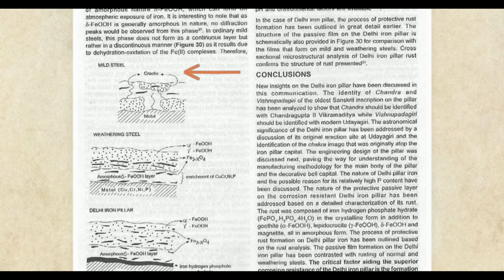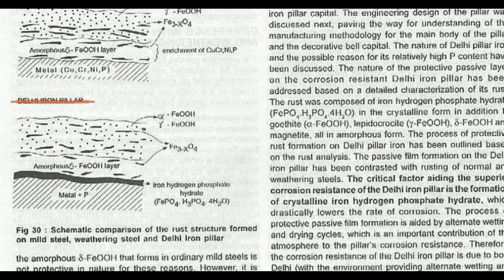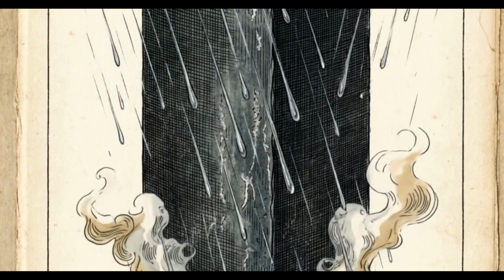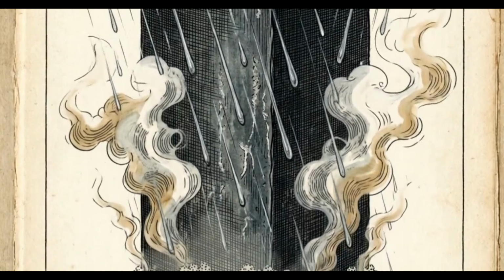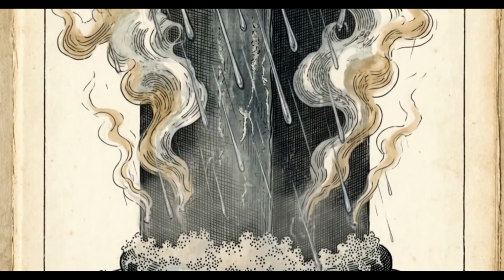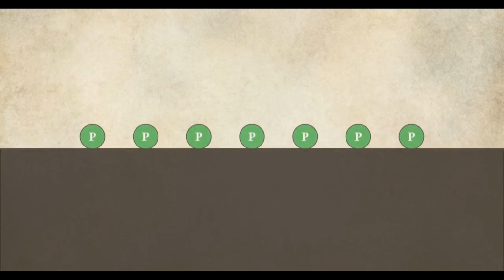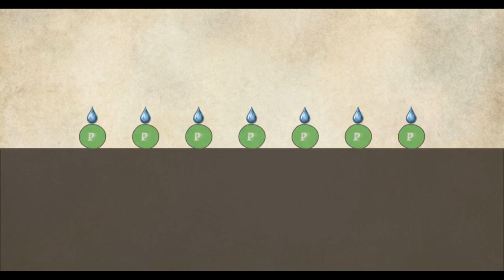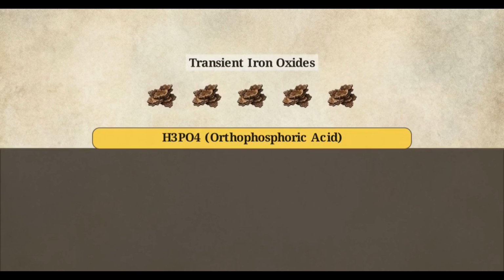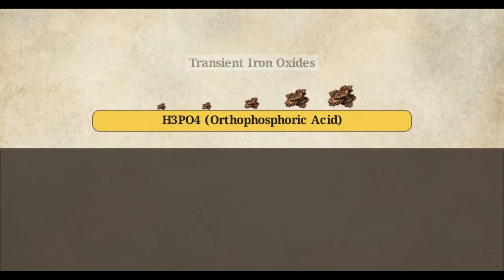While mild steel rust remains porous and prone to cracking, the Delhi iron pillar's layer is compact and protective. The concentrated phosphorus interface drives the formation of a dense, continuous layer of amorphous delta FeOOH directly above the metal. Transitioning to the next chemical phase required the extreme alternate wetting and drying cycles of the Indian monsoon season. As monsoon rainwater hits the surface, it initiates a hydration reaction, converting the enriched phosphorus into orthophosphoric acid at the metal interface. This acid attacks the transient iron oxides.